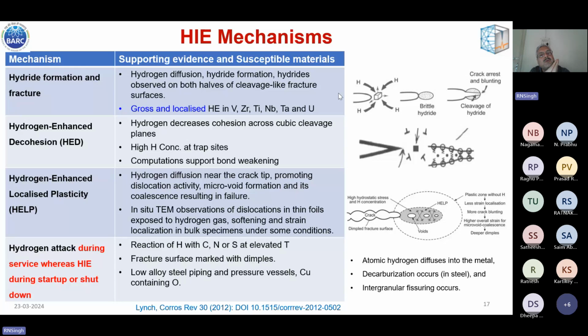But then people thought that if that is so, then fractographic evidence must be there. And on fractured surfaces, there were completely cleavage failures, oriented at different angles and all. So then they discarded this theory. However, in the case of hydrogen attack, the fracture surface does show dimples. So that is the experimental support for this.